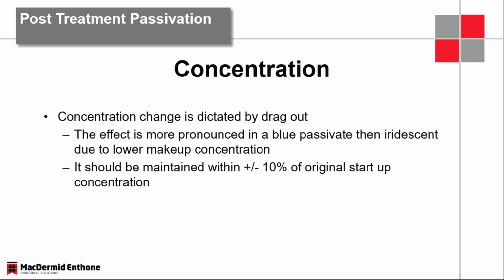Concentration. Yes, concentration is important. I'm not saying it's not, but the majority of the decrease in concentration is related to drag out, particularly in barrel operations. The blue Passivates that make up that 3%, 5%, 10% at the top are obviously going to be more affected, because when you drag out some of that solution, the difference in concentration due to drag out can be significant at a lower concentration of 3 to 5%, say, versus a higher concentration as high as 15 to 20%. It is going to have an impact, but it's not going to be as detrimental.